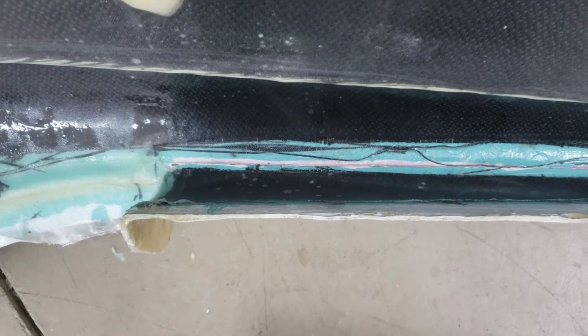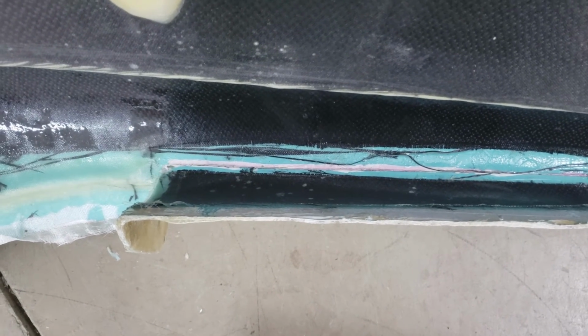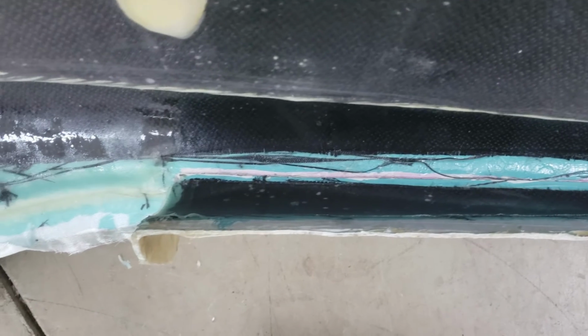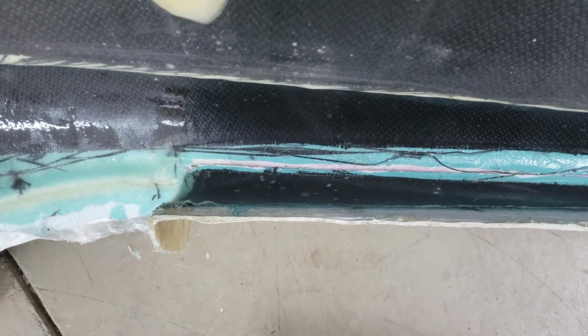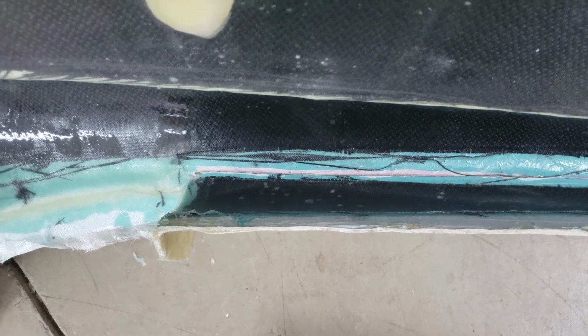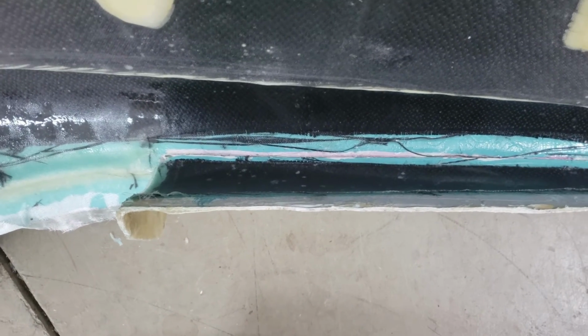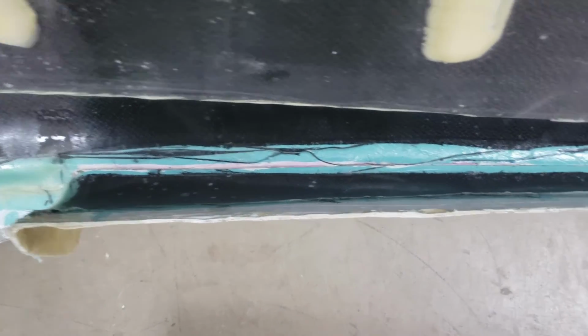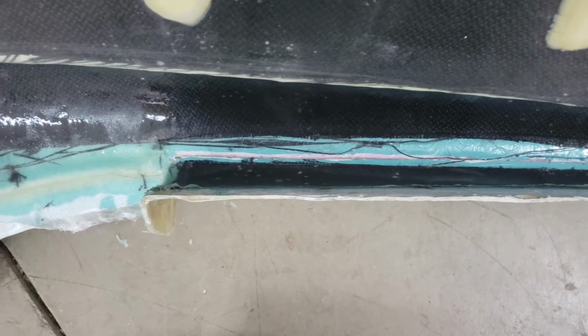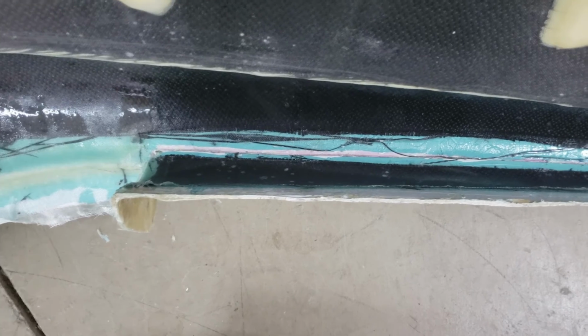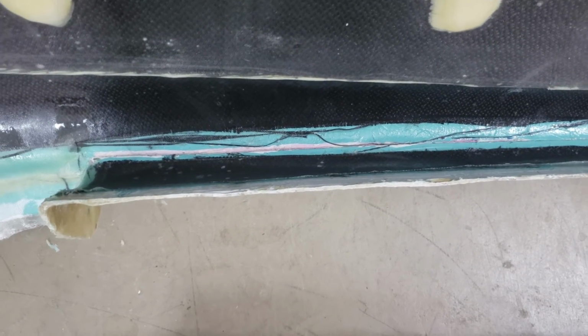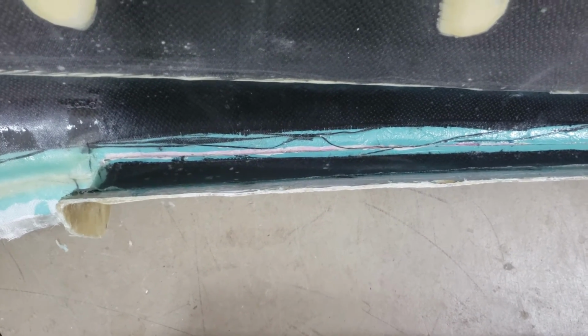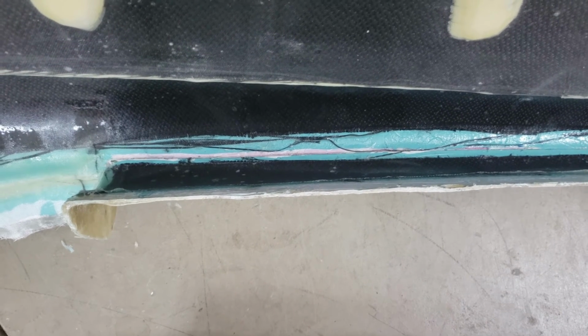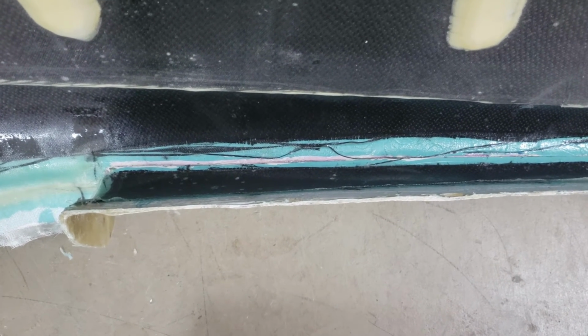So first step is to put just a little bit of gel coat in there to cover up the space that hasn't quite met all the way through the crack, and to fill that in. And then put a few layers of carbon fiber on top of that. More carbon fiber than what I put in the rest of the body. This is a stressed area, since you'll be leaning on this getting in and out of the car, so I'm going to put a few extra layers, and finally some ribs.